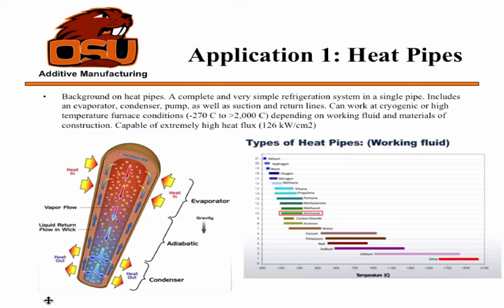So it's entirely passive, and you can actually look up the delta P's for wick structures for given parameters, basically. The other really cool thing is the temperature. They can work at cryogenic, negative 270 degrees C, where you use something like liquid helium as your working fluid, all the way up to furnace temperatures of 2000 C. You can actually use molten silver and molten lithium. So you're evaporating and condensing these different working fluids. There's a variety of working fluids.